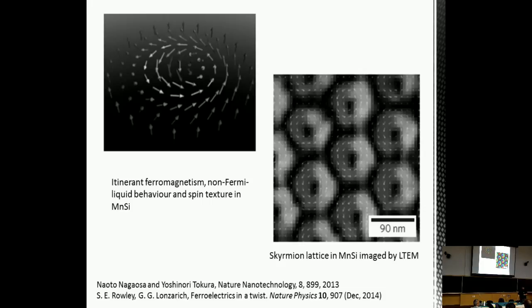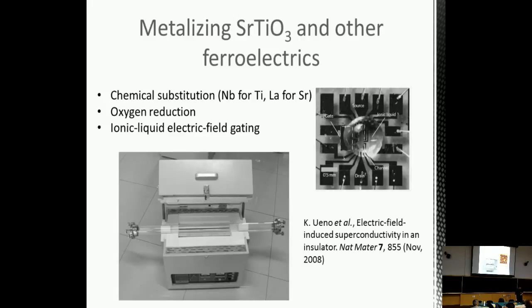Sure, yeah. So there are actually many different ways of getting these kinds of skyrmions or vortices in materials. One of the ways it can come from, as I mentioned earlier, is coupling to strain. So the strain field is highly anisotropic. And when you integrate out strain fluctuations and see what happens to the polarization, you can get these kinds of textures forming. But they can also show up purely from the phi-to-the-4 field model with no other fields. We can talk about that later.